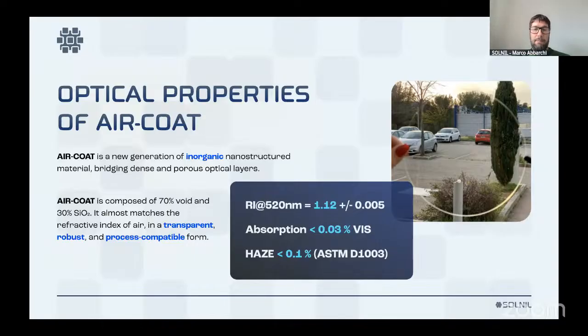So it is extremely low, but it has high optical quality. For example, the absorption is very low, below 0.03% across the visible spectrum, and the haze, which is associated to scattering, is well below 0.1%. This is comparable to the fused silica substrate. So you have a very low refractive index in a transparent and robust material and a process-compatible form.